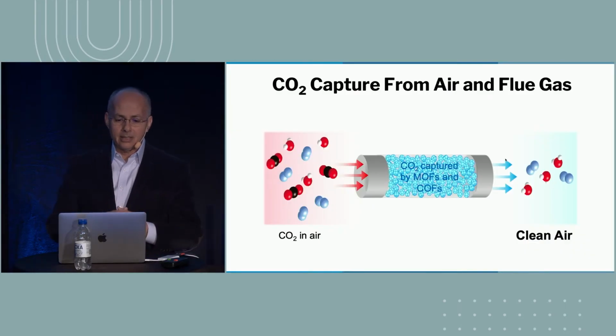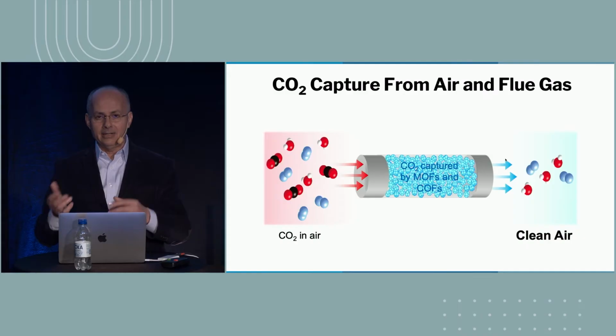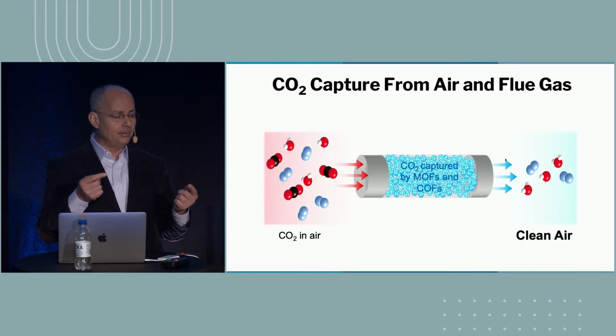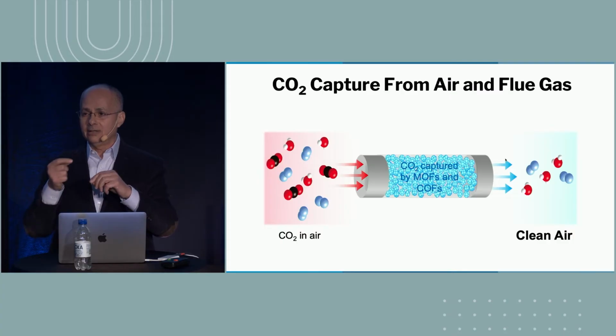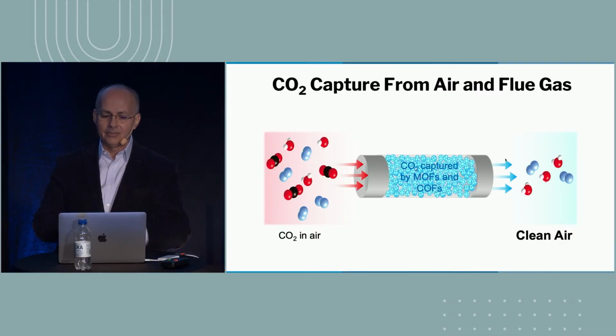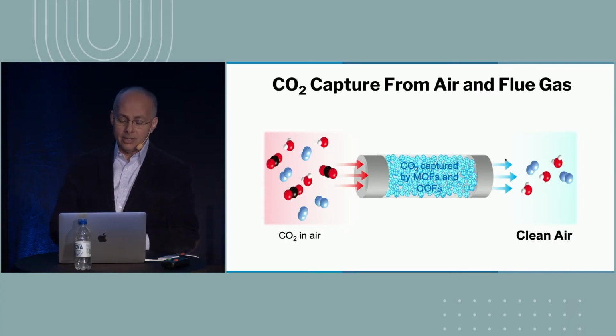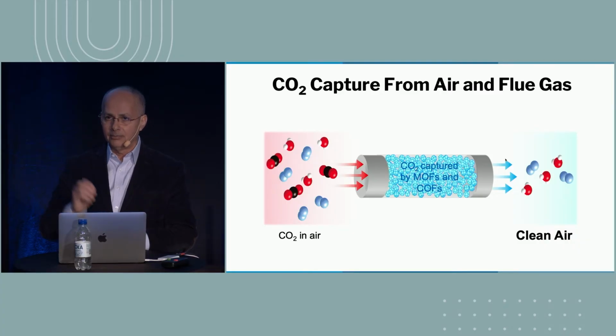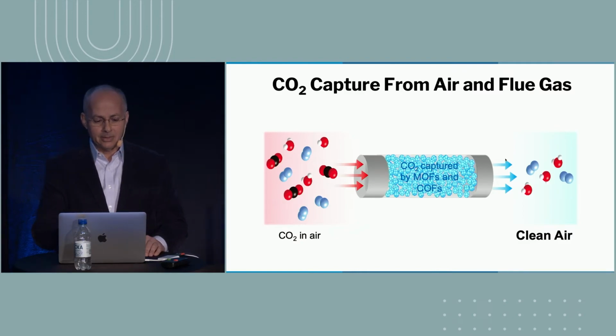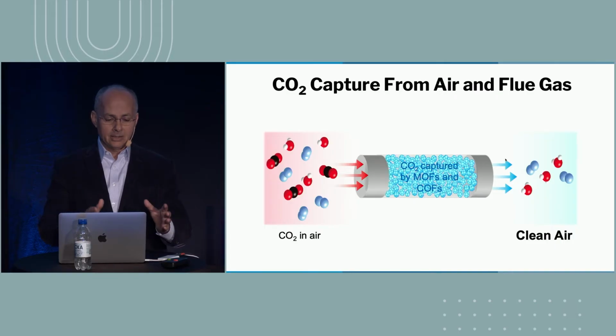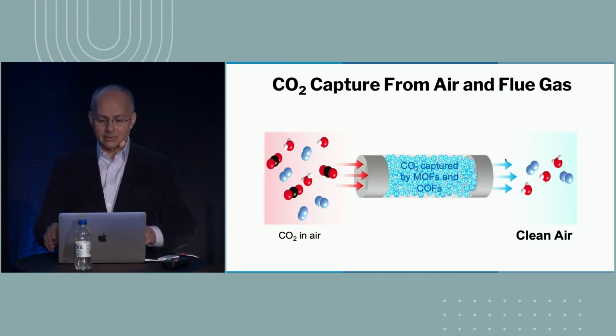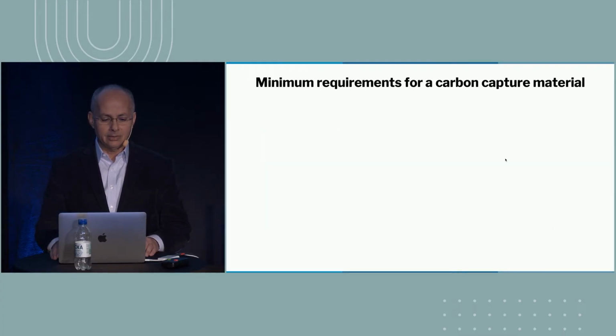Okay, so let's talk about carbon capture, and I want to talk about carbon capture from air. That's a more difficult problem than from flue gas. So if my material works in air to take CO2 from air, at about 400 ppm, it will work even much better if I put it in a power plant to prevent CO2 from going into the air. So this is the experiment that you have to do. This is ultimately the experiment that has to be done, where you take air, you put it through your material, and you look at what happens on the other side, if indeed it's trapping CO2 or not.